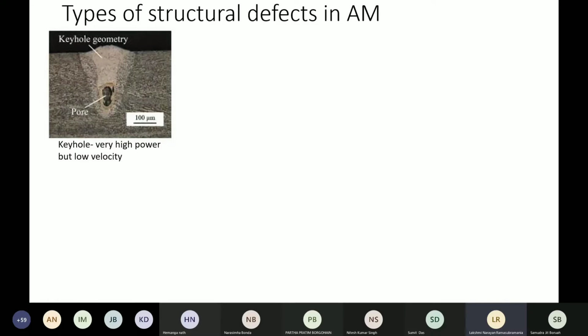So the first kind of defect that is always coming in is known as keyhole porosity. A keyhole, as you can see, is nothing but what forms when you use a very high power laser beam and a very low velocity. The power is concentrated at one spot for a long time, which means the laser will essentially heat a very deep envelope of material, which will result in this kind of geometry. Okay, a very high aspect ratio geometry. What happens is when this geometry is created, you always have a pore at the bottom of it.